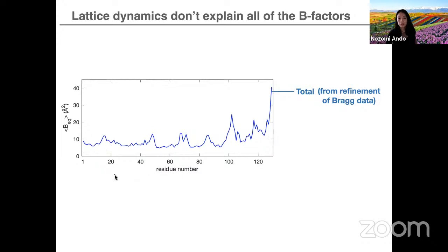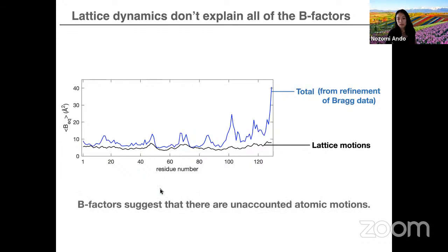If you calculate the B factors implied by the lattice dynamics model alone, you can see that a lot of the motion is actually explained by lattice motions, but there's still a difference between the two. So in other words, there are atomic motions that are not accounted for by lattice motions, even though most of the intensity of the diffuse scattering is explained by lattice motions. And so the question was, are the residuals due to protein motions?